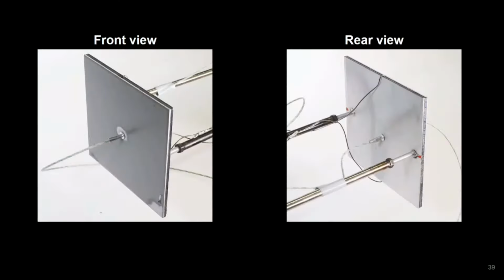The experimental specimens were square, flat samples of the respective products of interest with exposed edges of core materials, and these samples were either 100 millimeter square or 500 millimeter square. Reynobond PE samples were tested in 3 different configurations, namely a rear fixing condition shown here, with the sample supported from its rear aluminium skin, thus allowing for downward mobility of the front face of the sample on heating, and hopefully it will become clear what I mean when I show you some of these experiments.